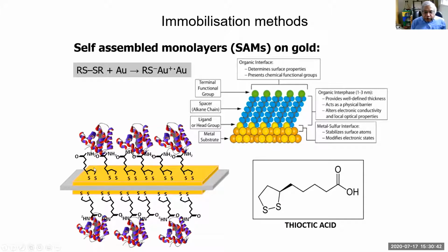And we've devised methods where you can take a molecule called thioctic acid. These sulfur atoms have a very strong affinity to gold. So if we have a gold surface, we can just treat that with thioctic acid, and this forms what we call a self-assembled monolayer. They assemble into this very regular structure, which allows us then to immobilize our protein at the end covalently. So we have a chemical reaction which allows us to immobilize the protein at the end of that chain.